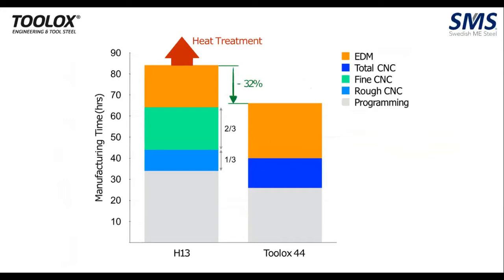So we come to this, wherein we look into the manufacturing time when you manufacture an H13 insert and then you want to use Toolox 44 against that. When you manufacture an H13 insert from raw material to finished product, the Toolox 44 has a definitive advantage. It is delivered at 45 HRC, and there is no two-time machining, annealed and after heat treatment. So it is only one-time programming. You can directly go for your final CNC.